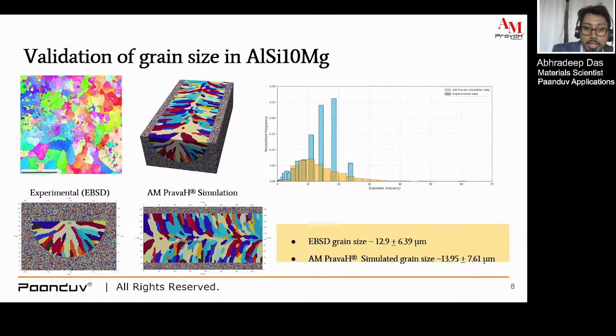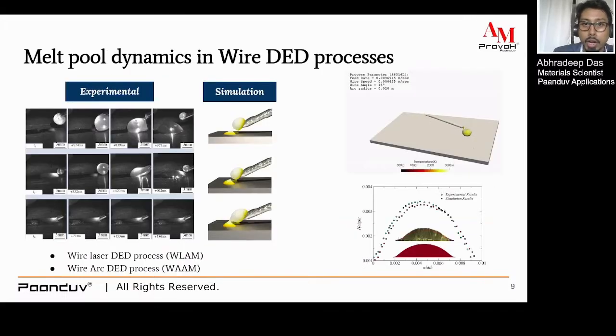Here is another validation that you can see, where we have accurately captured the deviations of the grain sizes as well, validated against the experimental EBSD analysis. We are modeling and simulating two different wire DED based processes, which are wire laser DED processes and wire arc additive manufacturing processes. These processes include different material deposition modes and cover different defects that are generated in them. We can also see here the close proximity between the experimental results and the simulation results, and we have obtained a very good fit between these two.